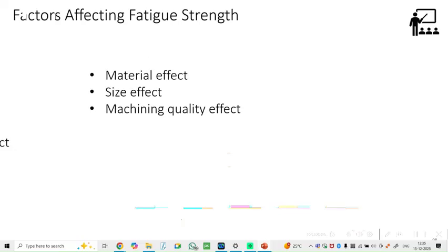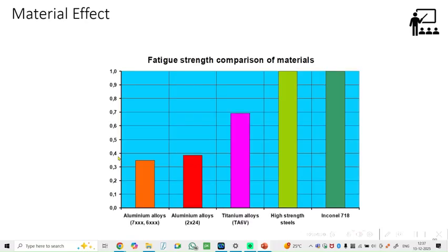So when you replace the high-strength steel with titanium, with the same geometry, the life will come down. It will reduce by about 30%. In aluminum, it will come down to 30 to 40%. So it comes down, and there is a lot of difference between the 7000 series and the others.